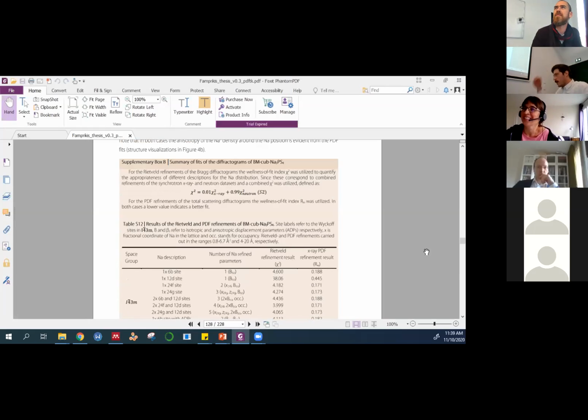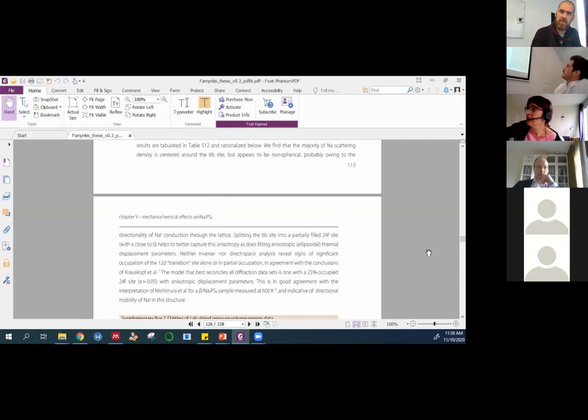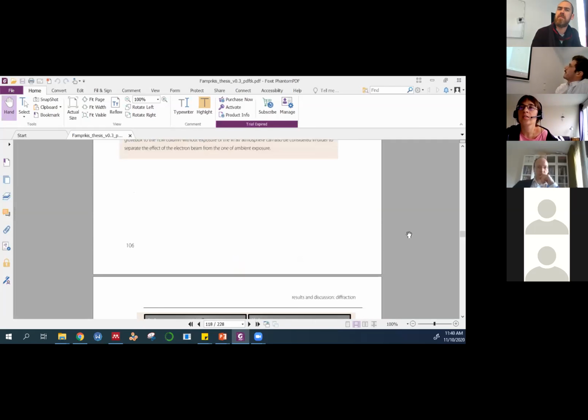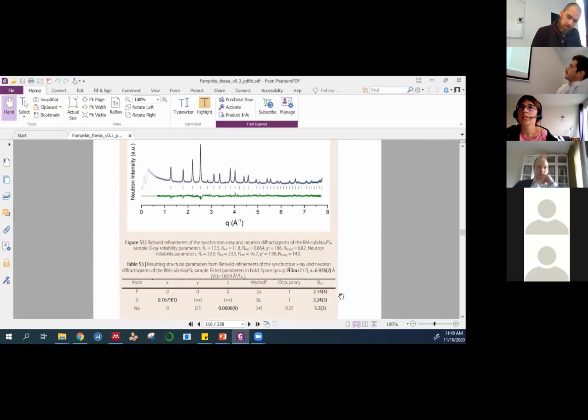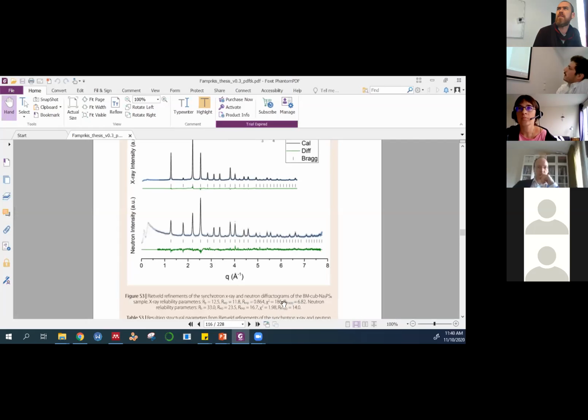No, not exactly. The reason why I chose this is that if you look at the actual fit of the diffractograms, the chi-squared factors that I get for the X-ray and the neutrons have about that ratio between them. The reason why I get such a big chi-squared factor, even though the fit is rather decent, has more to do with small imperfections in the peak shape, mainly at the feet of the peak, and the fitting of the background. So the 1% to 99% comes to somehow compensate for this difference.